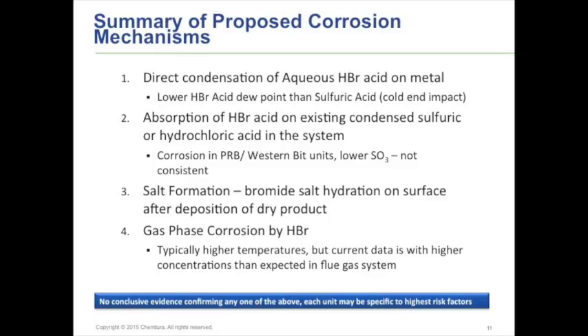The thought there maybe is that if you're already dealing with the acid problems because of your higher halogen coals, then you're maybe a little safer than when you're operating with low acid coal. With the coal handling equipment, pretty much nothing really was observed prior to bunkering, and a very small percentage was when they were adding it to the pulverizer.